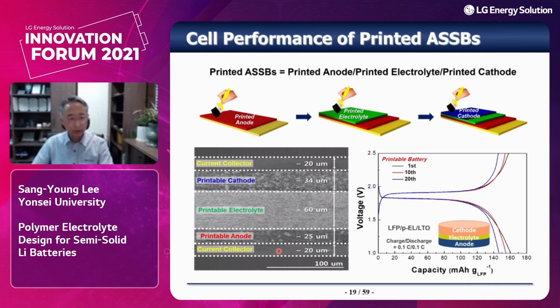As a first trial, unfortunately the thickness of our printable electrolyte was a little bit thicker. However, we have now reduced the thickness, which is similar to that of the conventional polyolefin separator membranes. Anyway, this printable electrolyte shows decent cyclability.